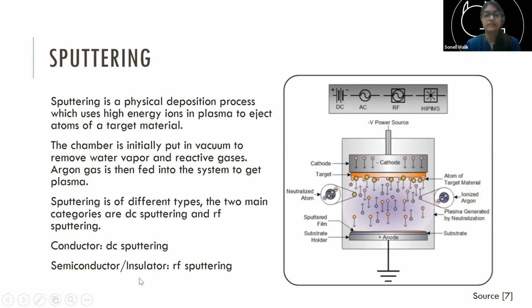So for semiconductors and insulators, the voltage alternates, and there is essentially no single fixed cathode or anode. In the cycle where the target becomes the anode, all of that charge is discharged. Then in the next cycle, when the sign of the electric field flips again, you again have argon atoms hitting your target, and you have deposition.